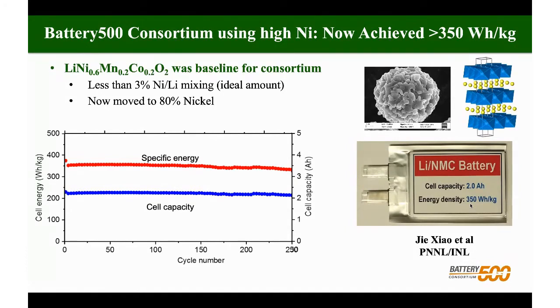And I should emphasize that this is a real capacity. So we get the capacity from the electrochemistry and the weight and volume of the actual cell. So everything is counted. The volumetric energy density of this particular one is about 700 watt hours per liter. And the cells were built in Pacific Northwest National Lab, and they're tested at the Idaho National Lab. So third-party testing, so totally independent.